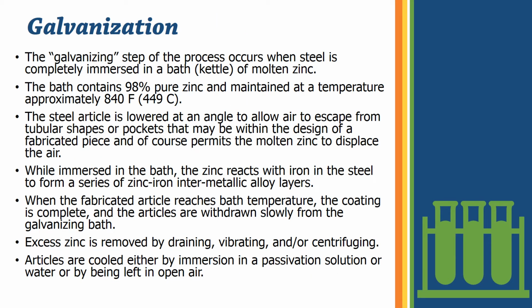The second and important step during galvanization is the main process of galvanizing. In this process, steel is completely immersed in a bath of molten zinc. The bath contains 98% pure zinc and it is maintained at a temperature of approximately 840 degrees Fahrenheit, that is 449 degrees Celsius.